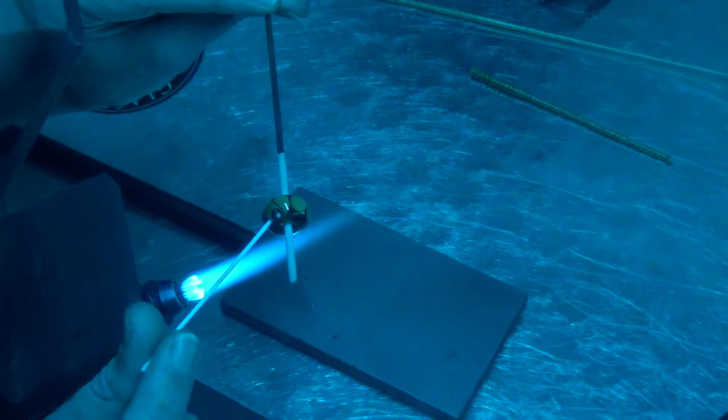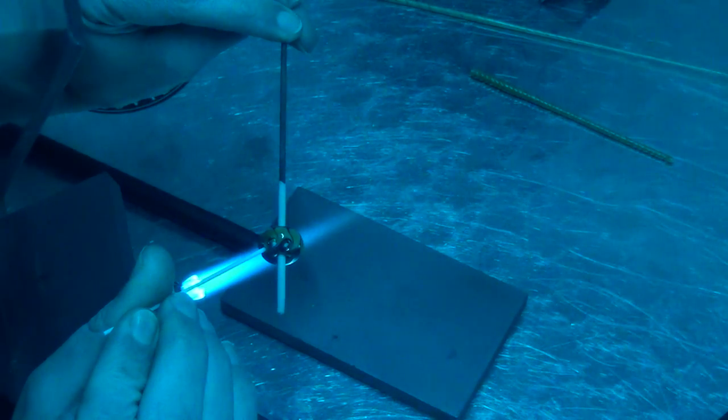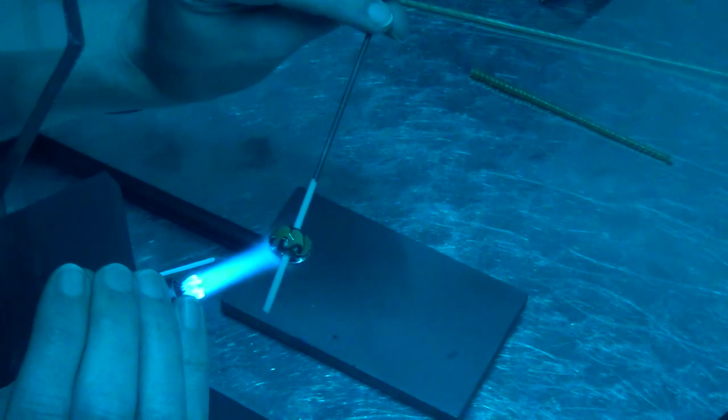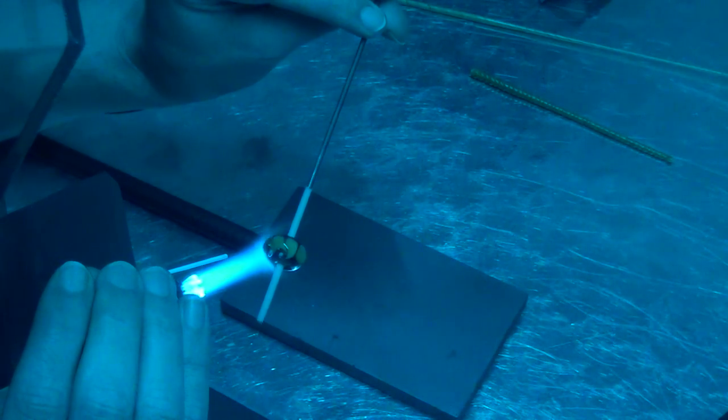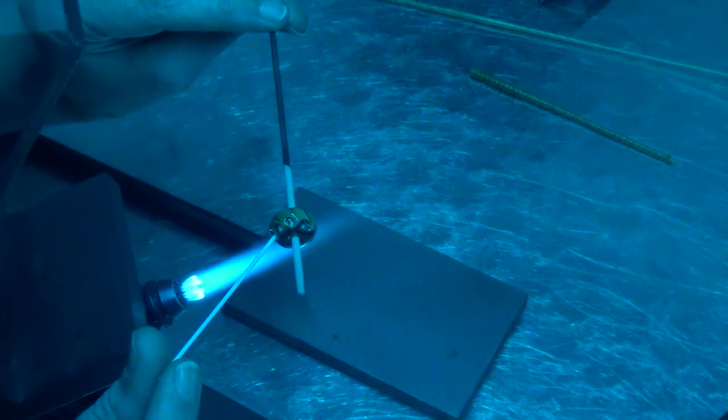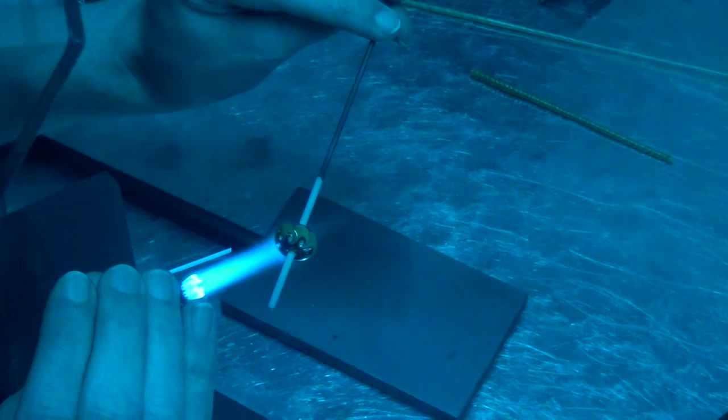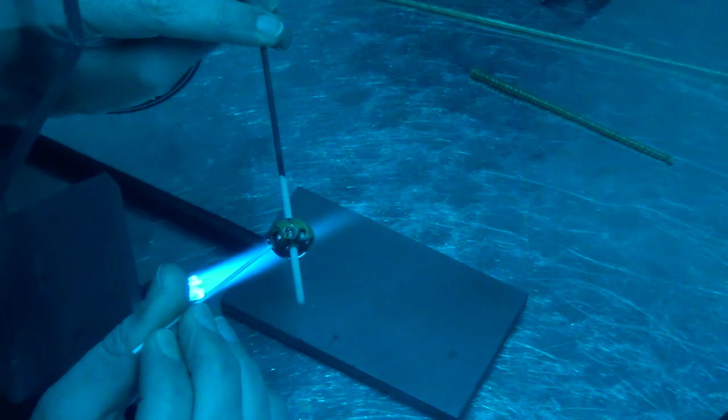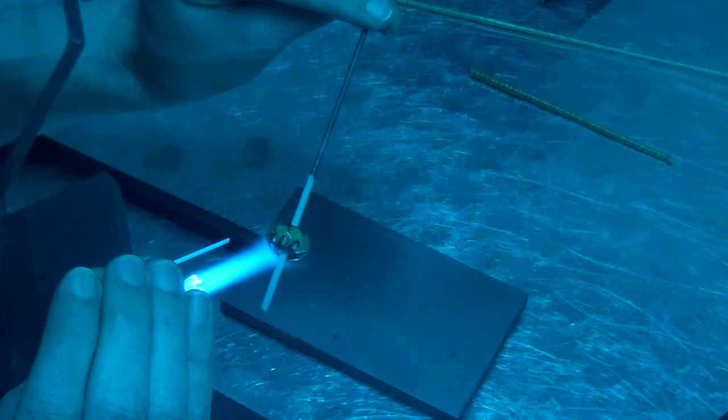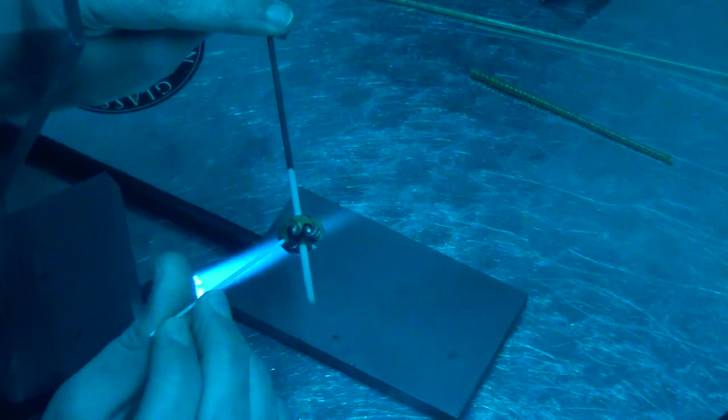And I'm doing this all the way around in order. Some people like to go back and forth to different sides of the bead, but if you do it quick enough, there's not really much risk of your bead cracking when you do this. So holding my hand on the marver, got my left hand on the table, and as long as you do this accurately and you get that stringer stuck down in the right spot, then this technique looks pretty nice. Now keep in mind that you're going to get a dot of color from the stringer left behind, and if you want to hide that then use a stringer of your base color. In this case I wanted the dots to be left behind to add some more pattern to it. That's just one of the variations you can do here.